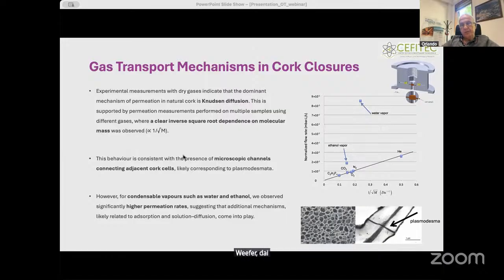However, vapors such as ethanol and water are very far from this line. And we believe that we have a second mechanism, solution diffusion. Water, for instance, has a huge affinity with cellulose, which is one of the main components of cork. And so it is understandable that we have another route for water transport. But for dry gases, and oxygen is the most interesting for this application, we believe at least our data is consistent with this model.